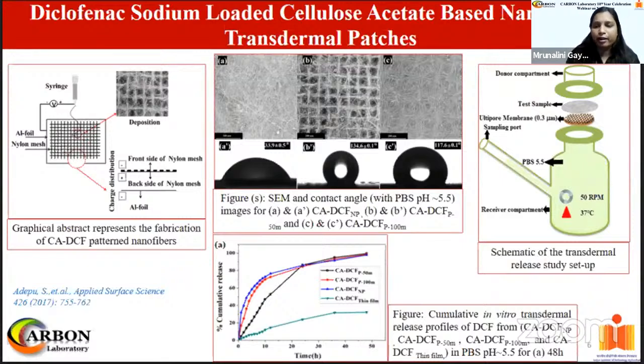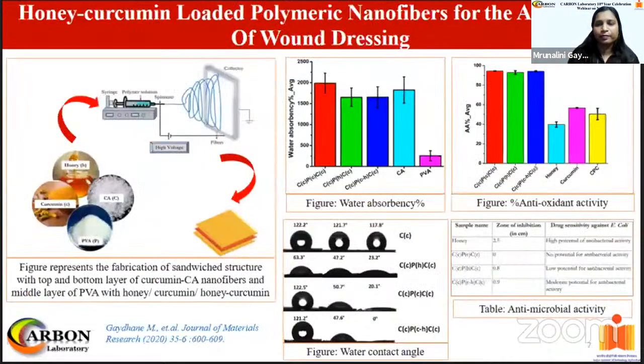Interestingly, the air trapped inside the interstitial spaces of nanofibers played a major role to control the burst release of diclofenac, which was not desired as it would have caused local toxicity due to its high concentration. Thus, we introduced a cost-effective technique to obtain patterned nanofibers, which can easily change the wettability of nanofibers and ultimately the drug release kinetics. On similar trends, we fabricated natural drugs, honey, and curcumin-loaded multi-layered nanofibrous mat as a wound